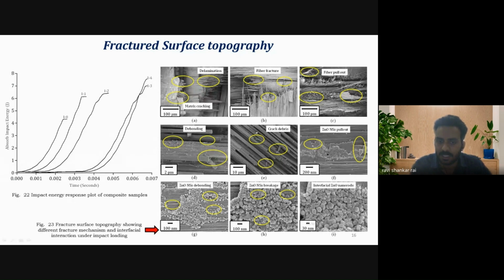These images are fractured surface images at the interface of the sample. So it was found that interfacial ZnO nanostructures are still available after the fabrication and after the fracture of the sample. So it is a very good surface topography for the development of high interfacial interaction.